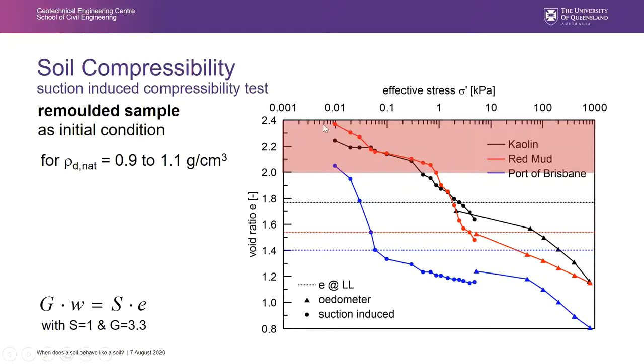And as you can see, we have here a very complex behavior. And regardless of the soil, we see very similar behaviors with three different kinds of inclinations. Also for the kaolin and for the red mud, it seems a bit different, but also here we have this kind of behavior. These are just as guides or best fits put in these transitions. And what is important to understand is that here we have a rather stiff behavior. So with increase of the stress, there is not a lot of change in density, but then within a small range, there is a large change in the density when we increase the effective stress. And then it turns into another mode.